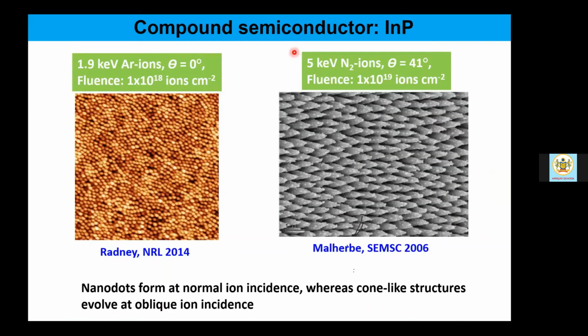Now let's take the example of another compound semiconductor, indium phosphide. At 0 degree incident angle, the dots are formed, while other authors have reported that using 5 kilo electron volt of nitrogen ions at an incident angle of 41 degree or so, with an ion fluence of 1 into 10 to the power 19 ions per square centimeter, the nanocones are formed. Very nice nanocones are formed. So nanodots are formed at normally incident ions, whereas cone-like structures evolved at oblique ion incidence.